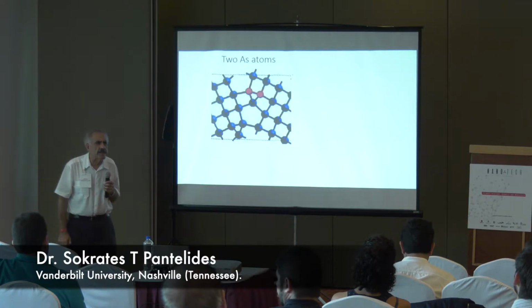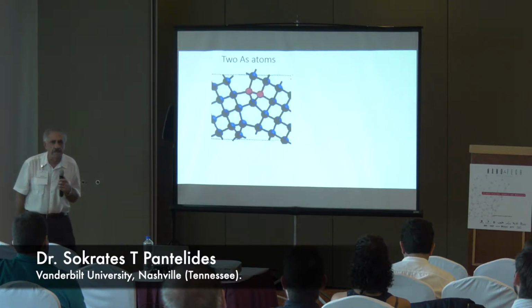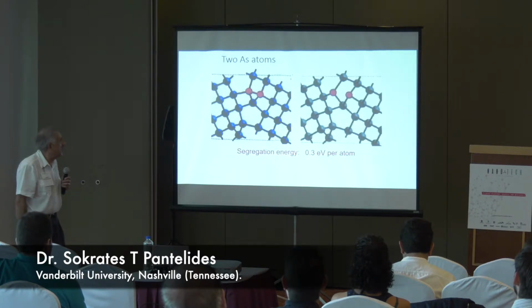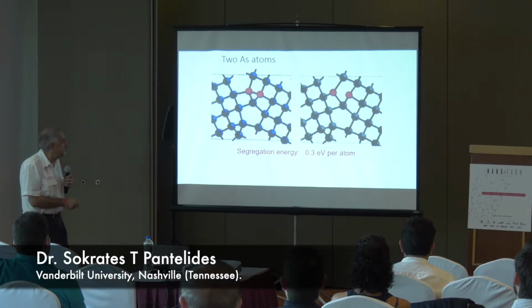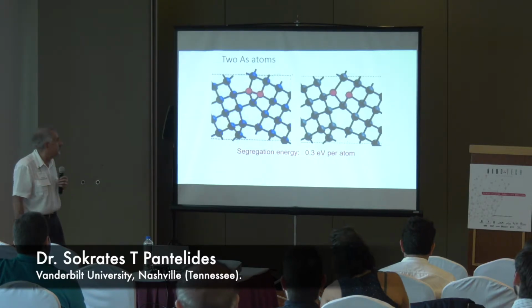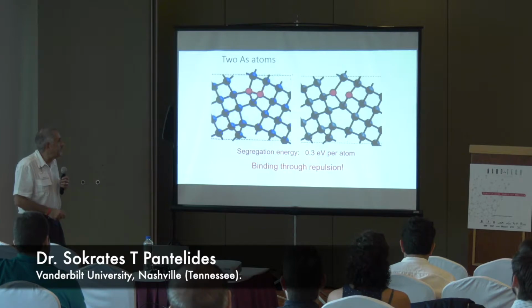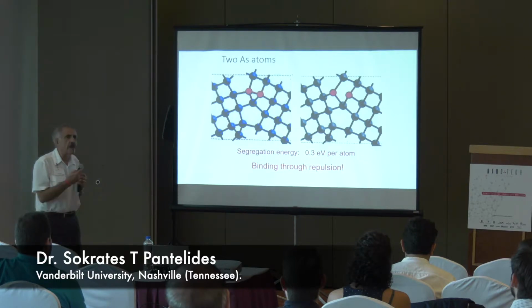So we said, all right, let's try something. And we tried putting 2 arsenic neighbors in there to see what's going to happen. And this is what happened. They pushed away from one another to become 3-fold coordinated. That's amazing. And we got a segregation energy of 0.3 eV, much larger than what we needed. And the amazing thing is that they are bound together by repulsion. Not by attraction. They repel each other and they get bound. So we are learning physics.